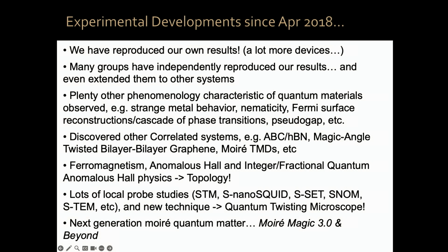Very interesting development, okay? Not only that, I've been talking as if we are always dealing with 2 layers, but why stop at 2? We can put 3 on top of each other, 4, 5 layers. It turns out the magic angles are different. For 3 layers it is 1.6 degrees, for 4 layers close to 1.70 something, for 5 layers 1.84. And the thing keeps going. So we call this the next generation Moiré quantum matter, Moiré magic 3.0, 4.0, 5.0, depending on how many layers you have. And many groups, including groups here at Harvard, my group at MIT, and plenty of others have been exploring this.